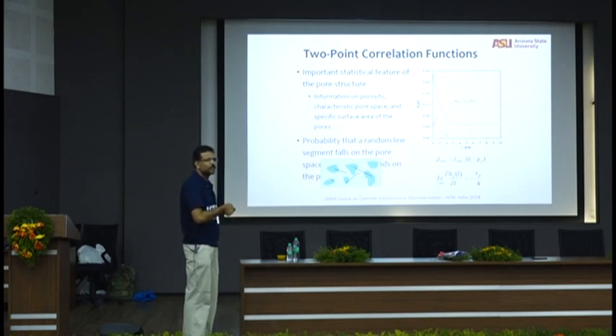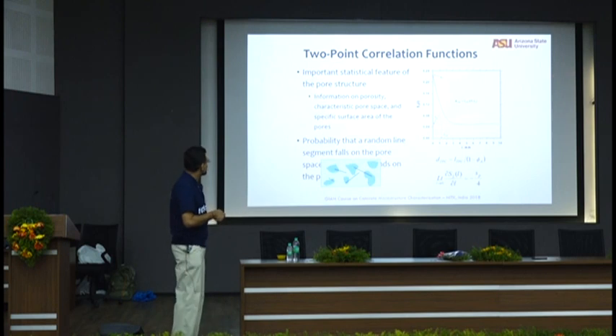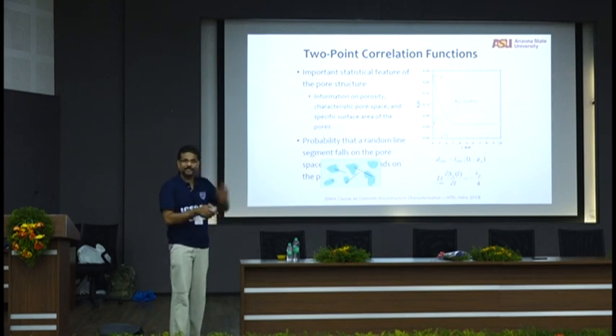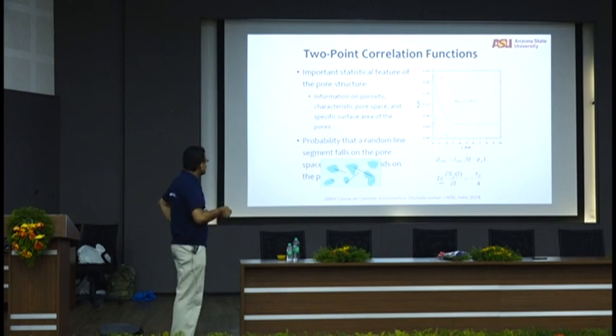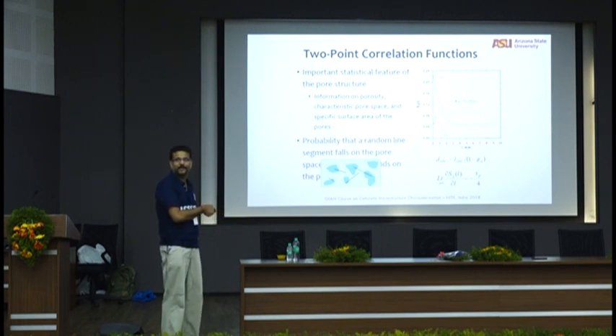But very interestingly, and this is universal theory, you will find out after some time, it doesn't matter what the length of the line is. Nothing changes. Right? You get a curve like this, and this curve is very interesting for two reasons. One, at zero length, lines are nothing but points, so I get the volume fraction, like I used to get last time, just throwing dots. The point where it is plateauing is the square of my porosity. That is always, and there is mathematical theory for it, the square of your porosity.